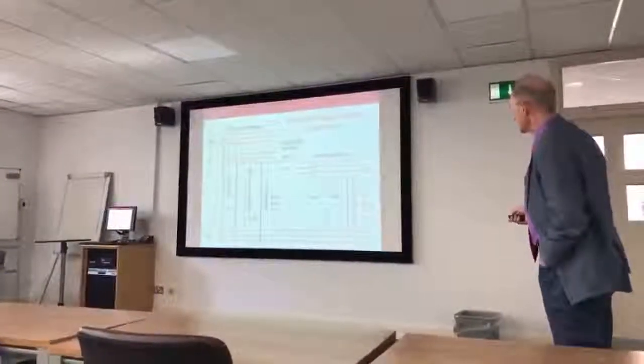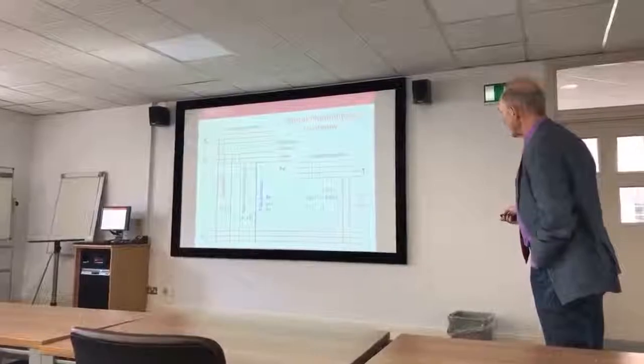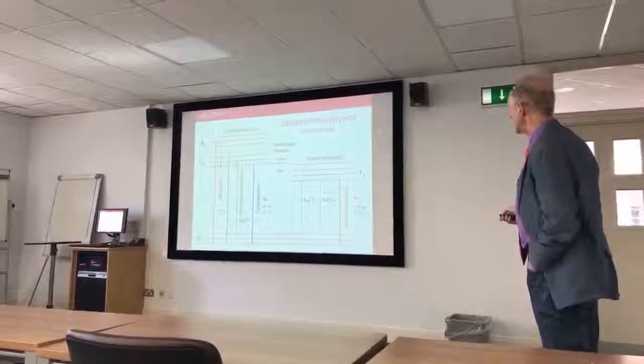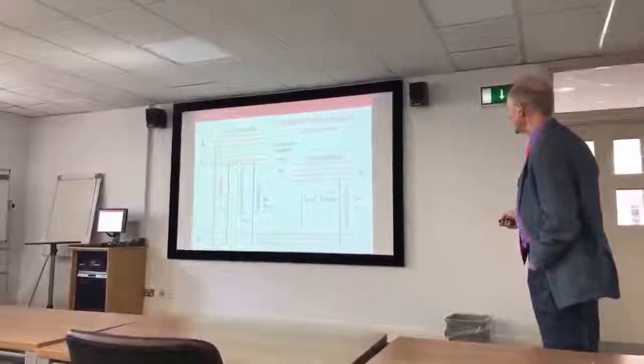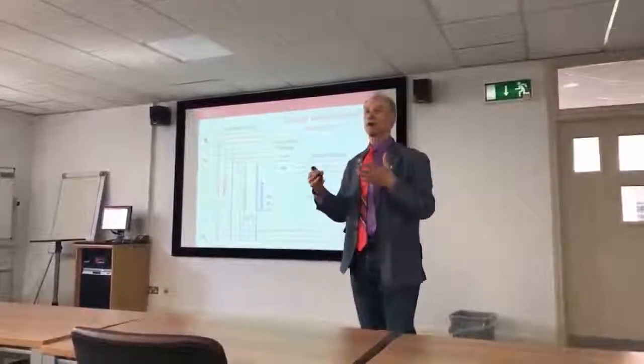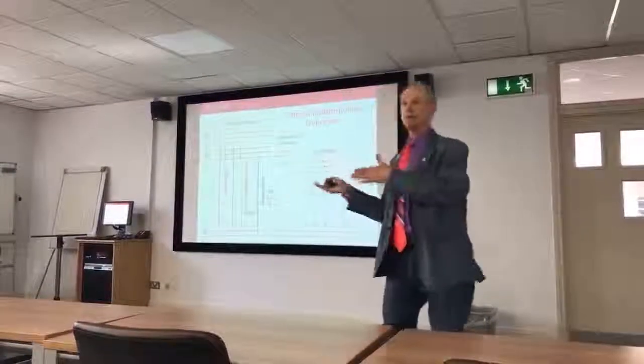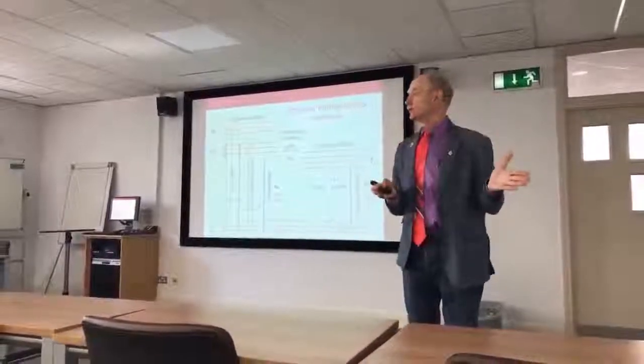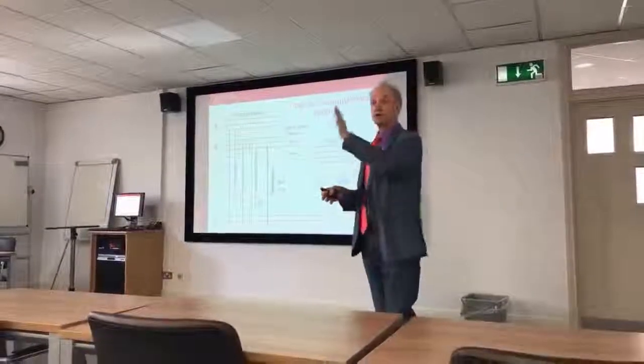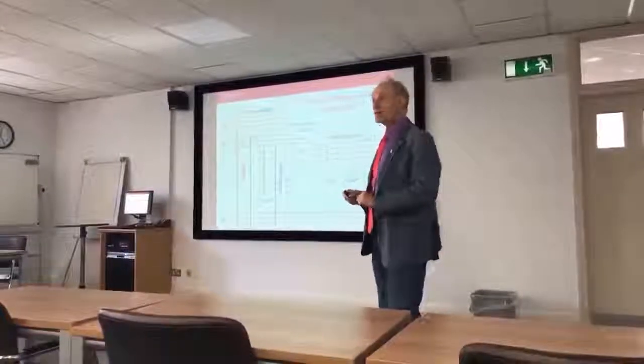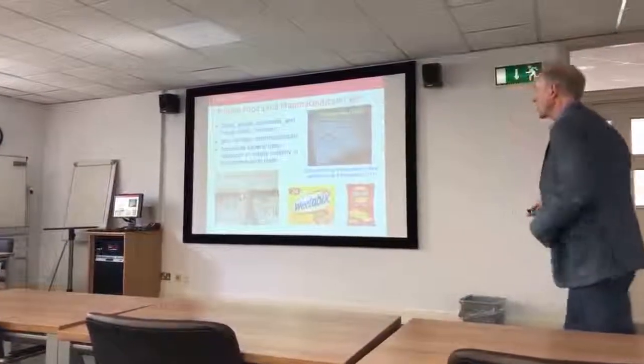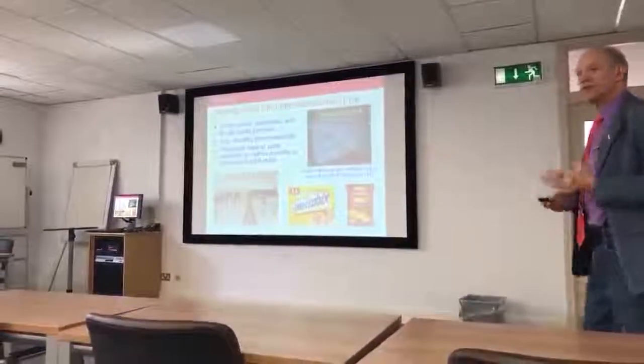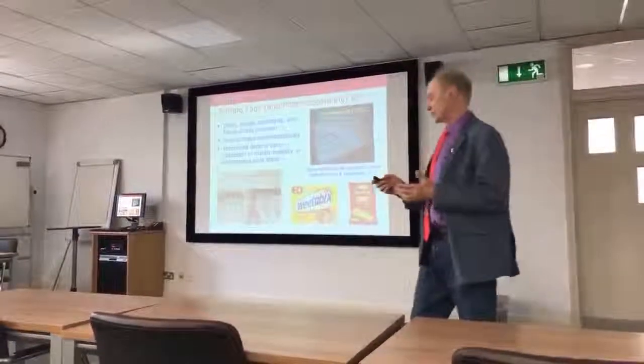But the final thing about the triplet manifold, and the most important thing for today's talk, is that a large amount of research over the last 50 years has indicated that this non-radiative transition from the triplet state is extraordinarily sensitive to local molecular motion in the matrix. For example, if you put a triplet state molecule in a liquid, it will be quenched very readily, but if you put it in a rigid solid, it will not be quenched. And so that's the first thing I want to talk about, studying amorphous solids by using phosphorescent probes.